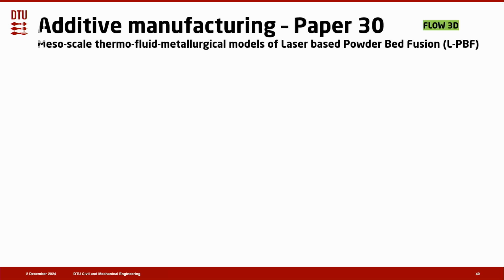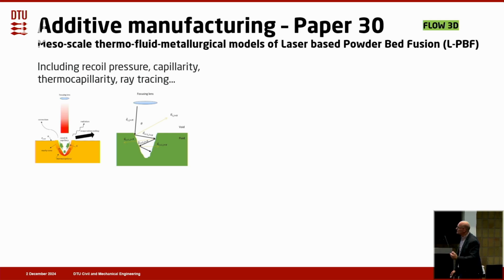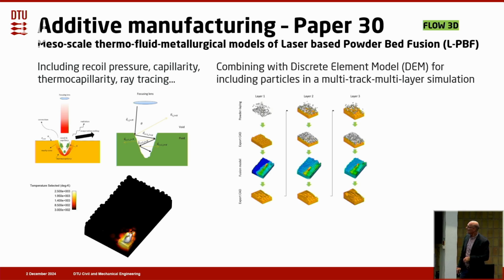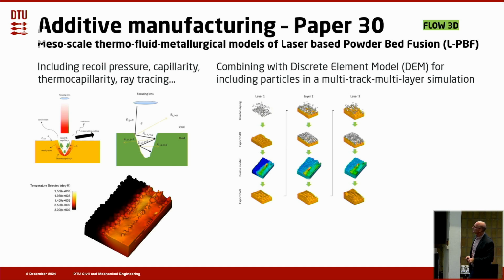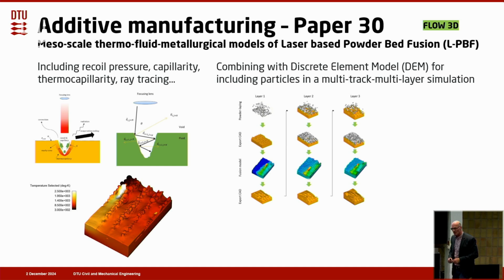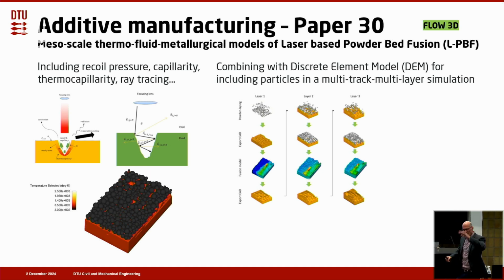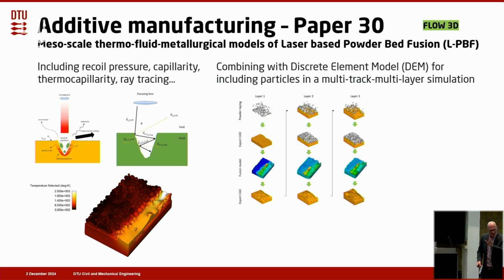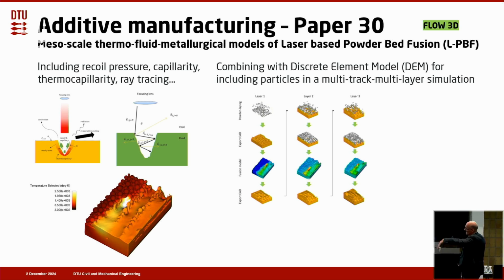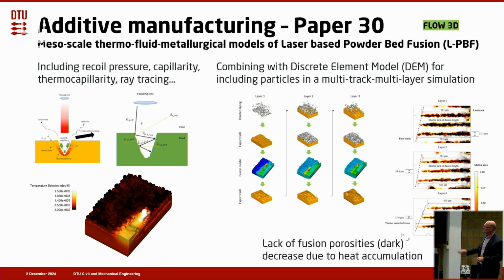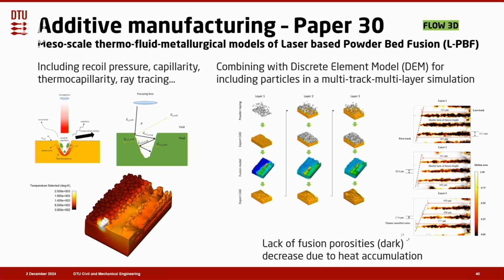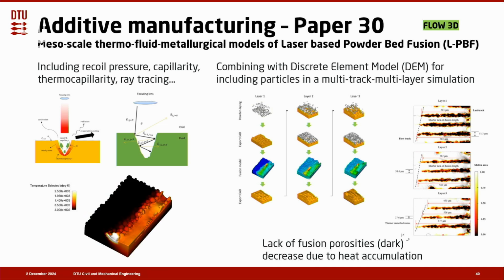So we continued with augmenting this model, making it more advanced, including recoil pressure, capillarity, thermocapillarity, ray tracing. And then we combined it with a discrete element model, including the particles in a multi-track, multi-layer simulation, quite advanced. So here you see the layer coming down. It's still just a mesoscale simulation. And then you have the laser scanning in different tracks, different layers. With this, we could actually predict lack of fusion porosities, and these are the dark ones. And of course, lack of fusion porosities decrease as you go along due to the heat accumulation once you scan on something that is already warm.